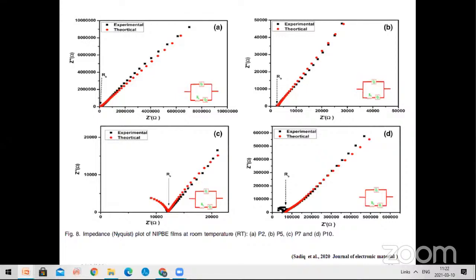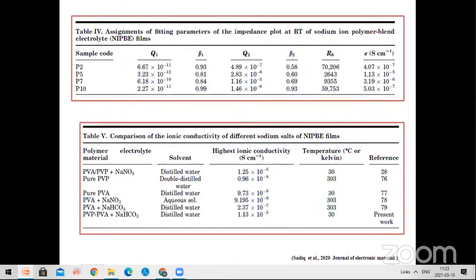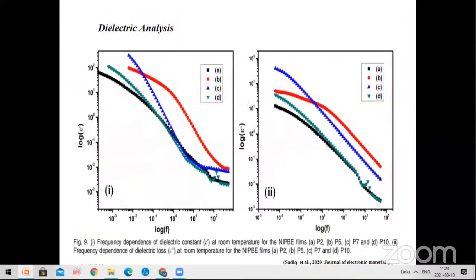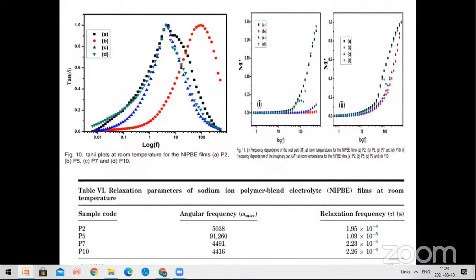This is the impedance spectra of the polymer films. Our conductivity is of the order of 10 to the power of minus 5 with the polymer salt complex. And these are some literature values we compare with our conductivity. We also find some dielectric parameters to analyze the dielectric properties of these polymer electrolytes. We take the tangent delta plots and find out the relaxation frequency of the polymer electrolyte film. These are the parameters we find: the relaxation frequencies and their angular frequency.